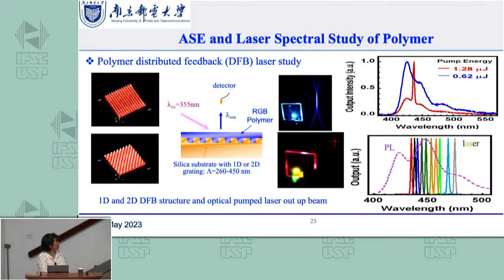So that's the optical pump comes this way, and this is a film, and the detector in this side, you can see the laser like that, and you can take the laser spectrum. You will see a sharp spectrum come out. Below the threshold, there's just a normal luminescence, the PL spectrum. Once you reach the threshold, you can see a sharp peak come. And this wavelength, the output laser wavelength, can be tuned by changing the period of the grating or the thickness of the film.